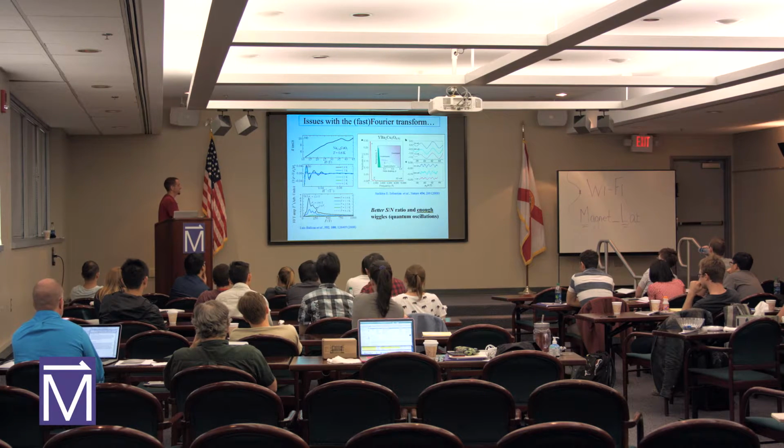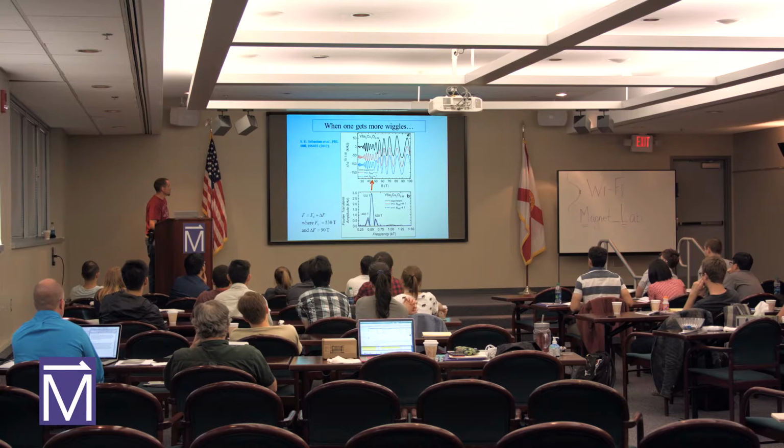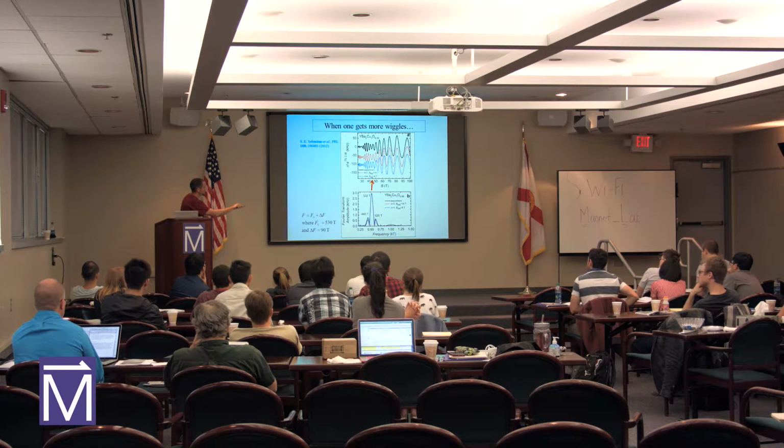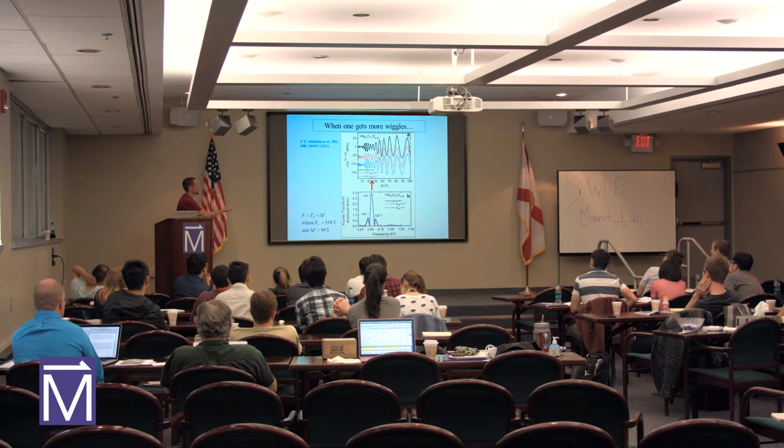In Suchitra's case, she took the same type of material out to Los Alamos. And you can see this is the stopping point for the hybrid magnet. And she picked up 55 Tesla of additional information by using a pulsed magnet to 100 Tesla. Okay, having the additional magnetic field certainly gave her more quantum oscillations.